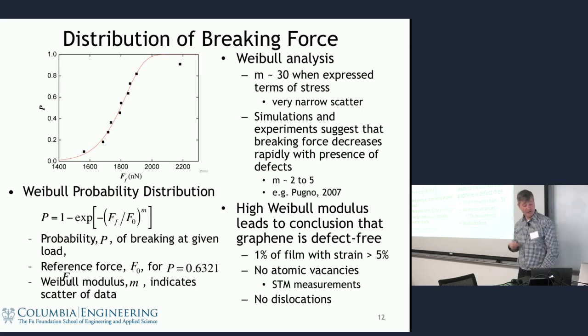So that Weibull analysis, as well as just the size of the breaking strength, led us to believe that we were not measuring what you measure in every other material, but we were measuring intrinsic breaking strength due to the breaking of all the bonds at once, rather than propagation of a crack.